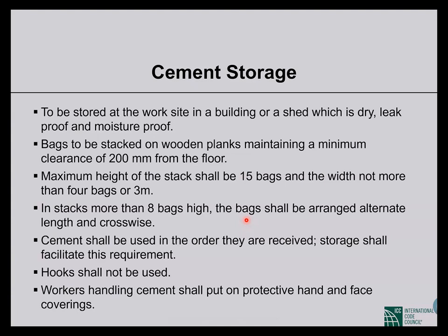Maximum height of the stack shall be 15 bags and the width not more than 4 bags or 3 meters. So we can stack one bag after another on top of one bag, but the total height must not exceed 15 bags.